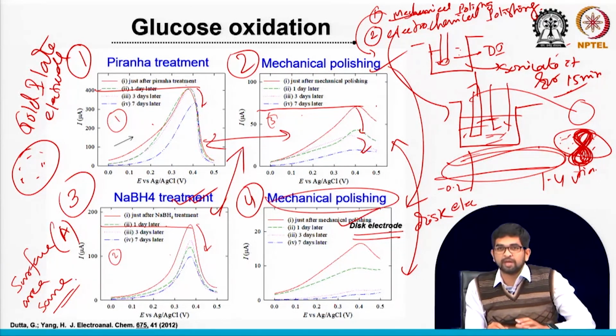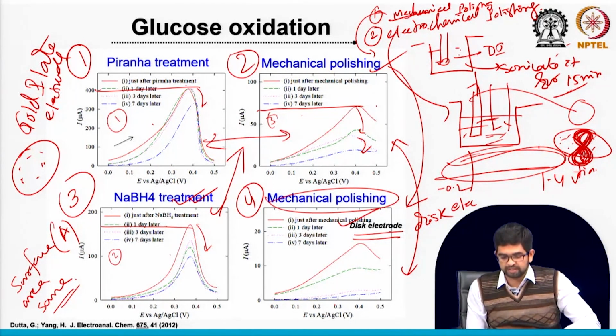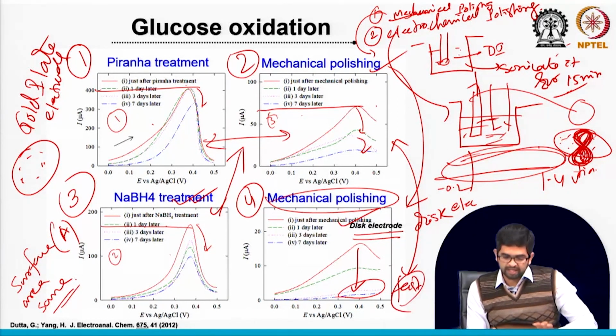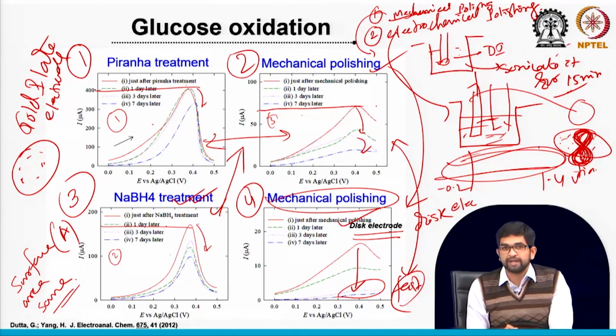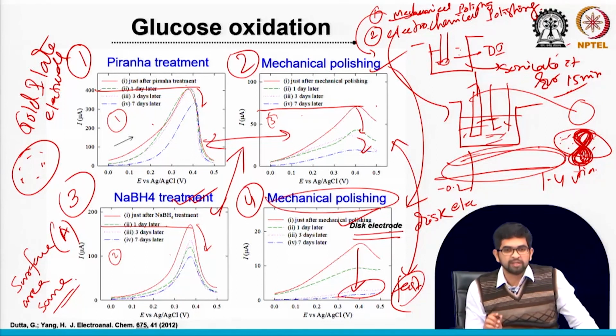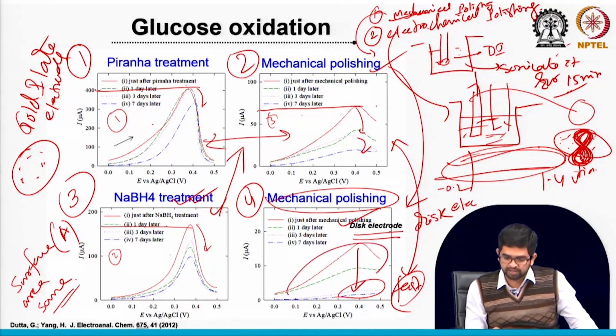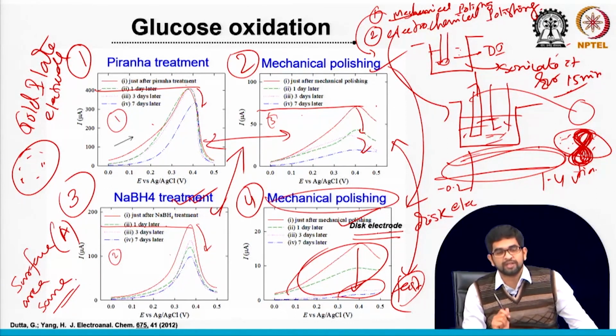Then after storage at room temperature in the laboratory environment, you can see the deactivation. In this case, the deactivation is also very fast. That's why mechanical polishing pre-treatment followed by storage for a longer time is not recommended. You have to take care of this electrocatalytic activity, otherwise you may not get reproducible data if you store it for a longer time. It's very important information. That's why you have to keep aging in mind while you are developing the sensor.